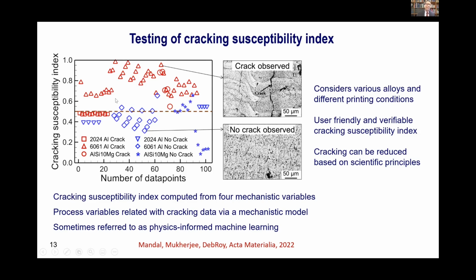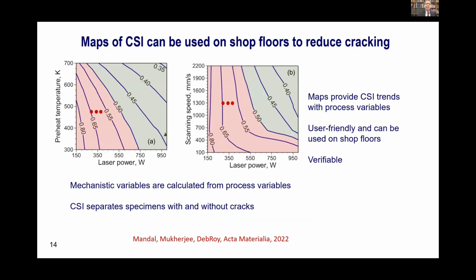We plot cracking susceptibility index on the y-axis and number of data points, and you can see that samples that had cracking susceptibility index greater than half showed cracks, pronounced cracks. And the samples that had much lower value, we did not see any cracks. So 4 mechanistic variables can clearly delineate cracking from samples where we did not see any cracks. So it is verifiable, it is user-friendly, and it is based on scientific principles.